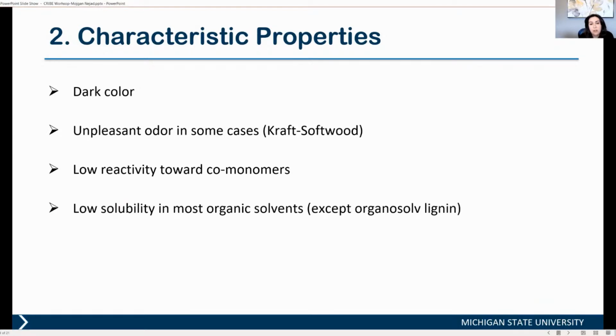Solubility is another challenge. If we cannot dissolve lignin either in an organic solvent or in the reaction media, which in some cases could be high alkaline pH, for example in phenolic resin formulation, then this low solubility is significant. It's going to impact reactivity and therefore the performance of the final products. Inconsistency is another challenge. If, for example, a company is producing kraft softwood pulp and changes the softwood species or uses different material, it's going to affect the properties of the lignin. And if they change the parameters of every single isolation step, it's going to change the properties of the isolated final lignin too.